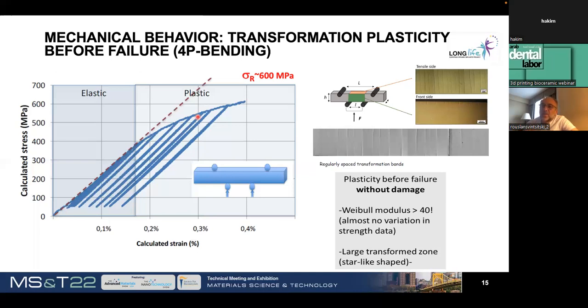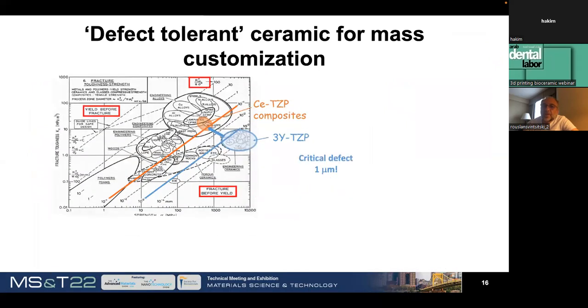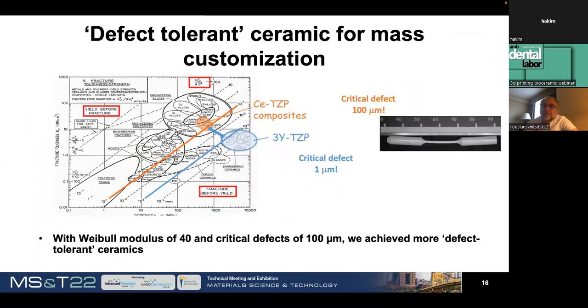So it means that on this diagram, when we tested this new material, ceria-doped zirconia, we could obtain a ceramic whose behavior is much better than for traditionally used zirconia. It means that with this Weibull modulus of 40, with this strength and toughness, we could obtain a material which is closer to cast iron than to ceramics.